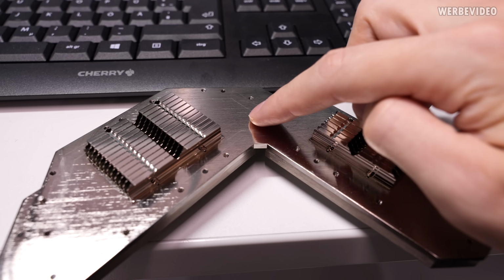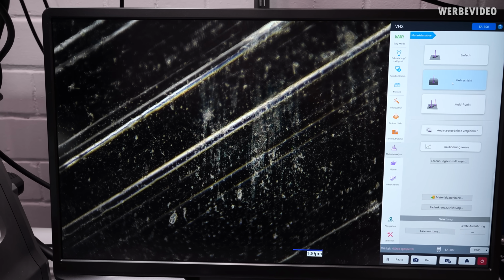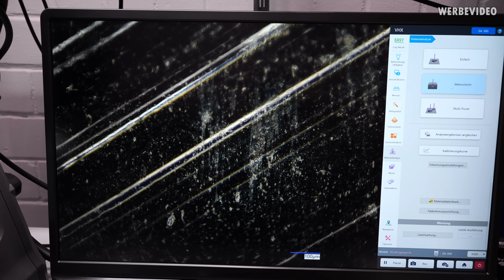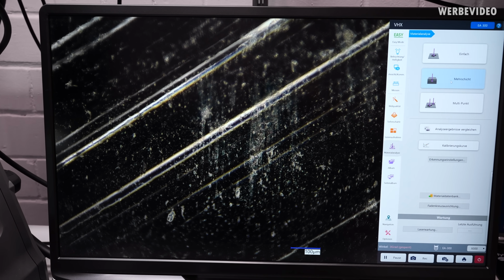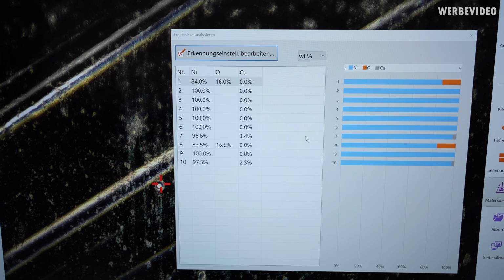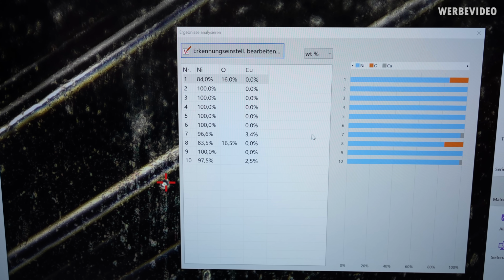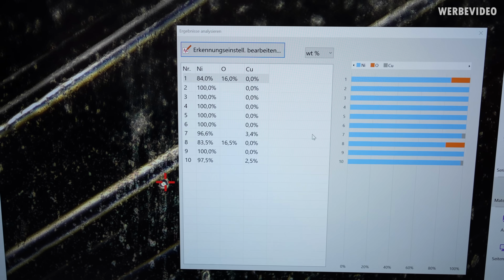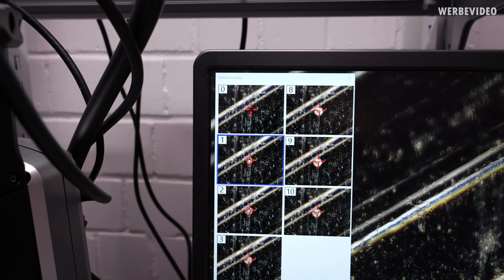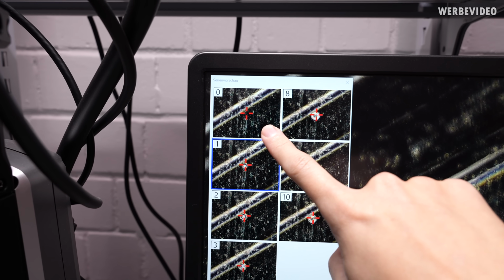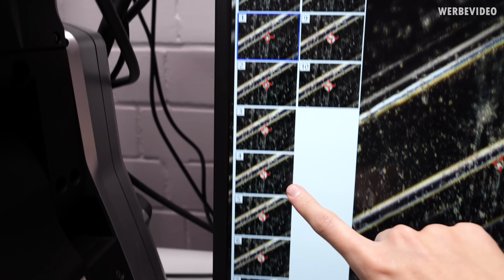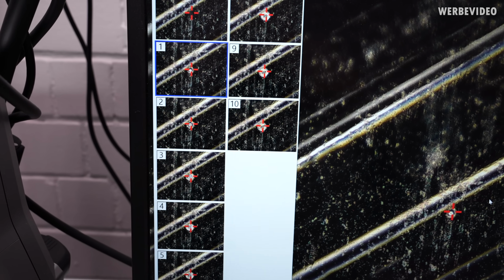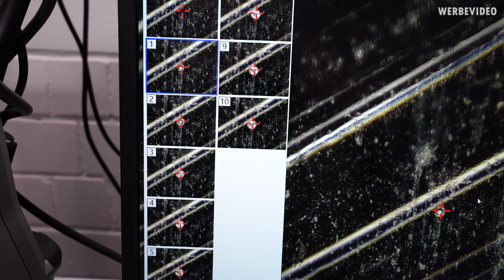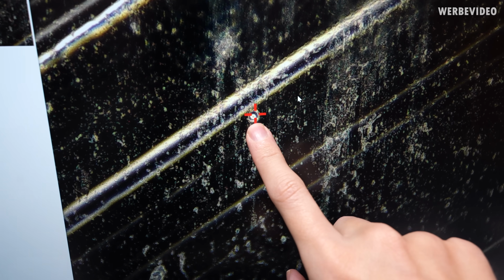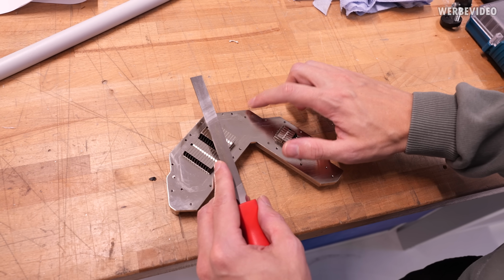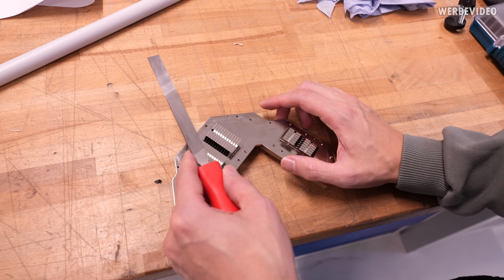So next up, we will repeat the same testing in this area. That's this area underneath the microscope, 300 times magnified, and we will repeat the multi-layer analysis. Quite interesting. So I repeated the test 10 times. It's definitely taking away some material, but it's still nickel. So very, very strong nickel layer. There you can also see it on the images. So that was prior to using the laser on the material, and then all the way down to trial number 10. There we can see a hole that we created, and that's what we can find also in here. I'm just using a file to rough up one of the edges to see if we can get through the layer quicker.